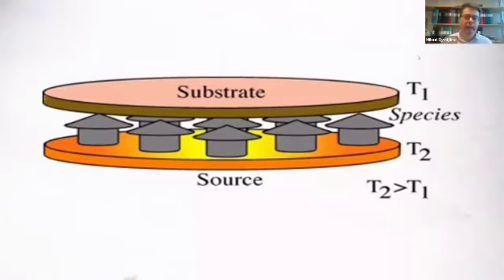And for silicon carbide, when you have power devices, and if you want to transform 10,000 volt, then you need very thick layers. And that was a big challenge at that time, and still is very difficult to control very thick layers grown at high growth rate. But this was a part of my PhD thesis, to explore such sublimation epitaxy for thick layers of silicon carbide.